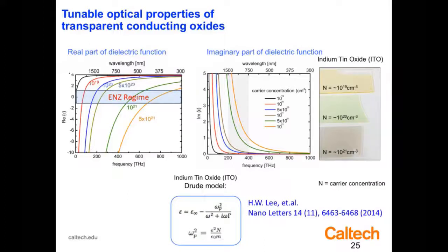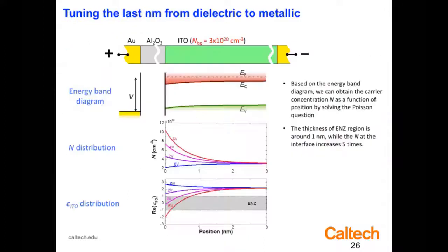So, this was done by chemical doping in ITO. We're going to see in a minute we can do this electrically as well. And the way we do this electrically is we now take this ITO film and we turn it into a little transistor. We turn it into a transistor that has a gate insulator, and now the semiconductor is not silicon or some other semiconductor material, it's ITO. So what we're doing is the same thing you do in a field effect transistor. You're bending the bands, and you're accumulating and depleting carriers at the surface of the ITO using this gate, which applies a field across this gate dielectric.